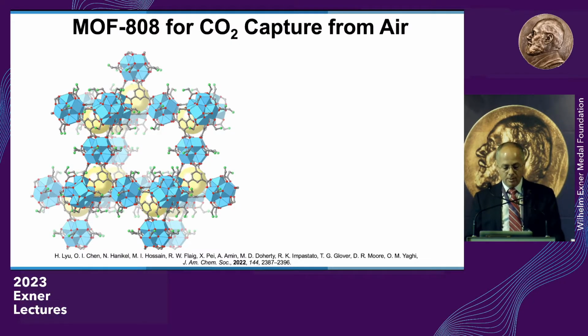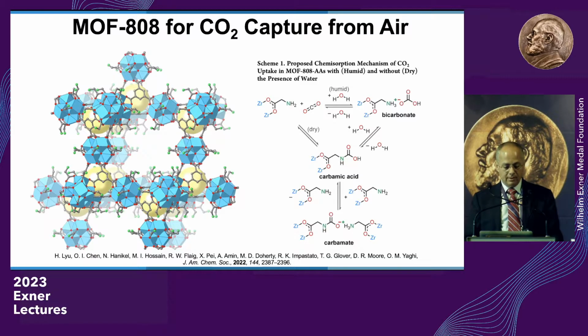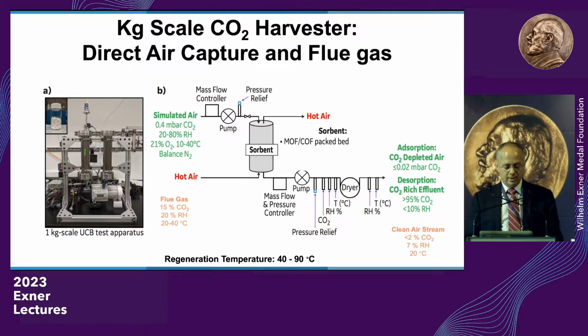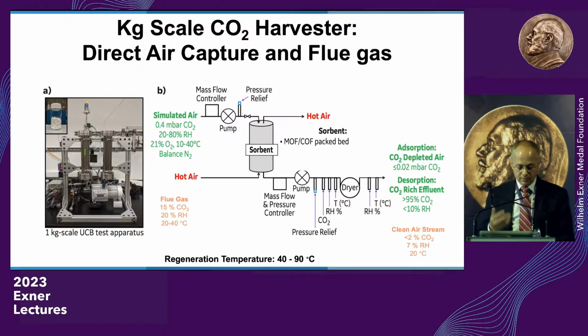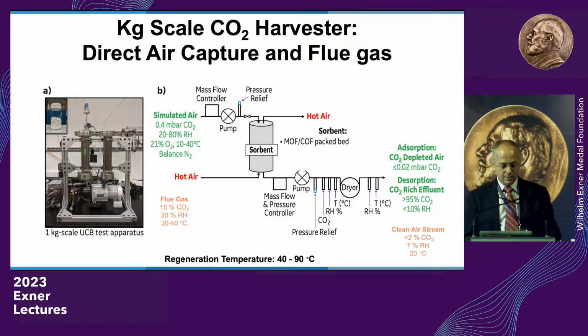We scaled up to a kilogram quantity, and we built a prototype in my lab to show that, in fact, this MOF can trap CO2 from air. Here's CO2 at 400 ppm with some humidity, typical of what would be, so this is basically air. And we pass the air through the MOF, and you can see that the amount of CO2 at the end is less than 0.02 millibar because of the binding of CO2 to the pores from air. So it works, okay? And in fact, you can repeat this process 80 times. You can take in the CO2 and remove the CO2, take more CO2, remove that, and so on.